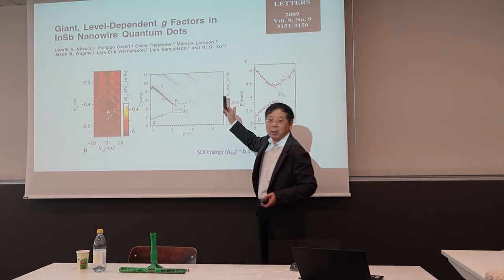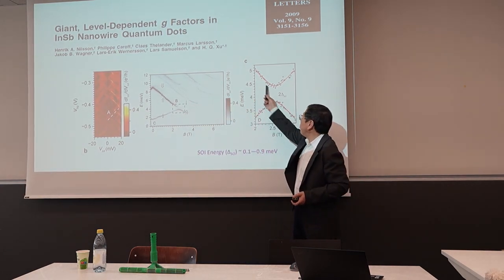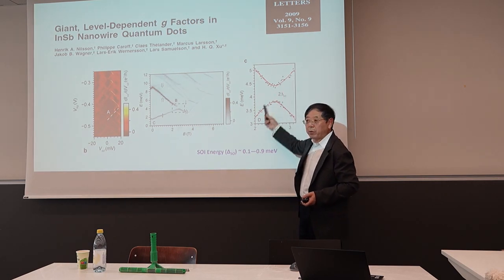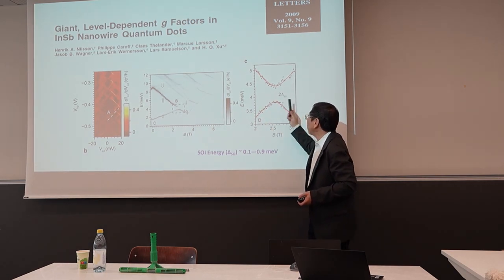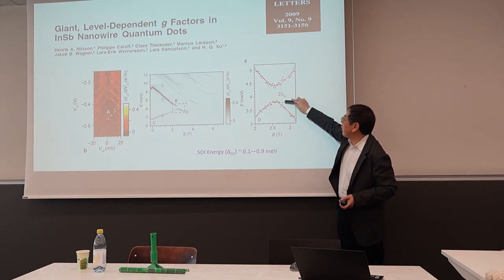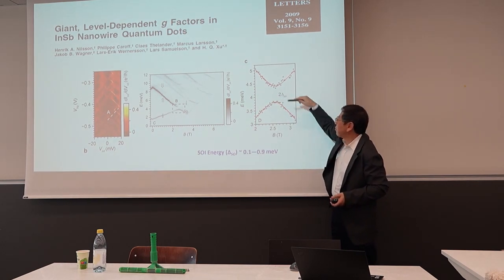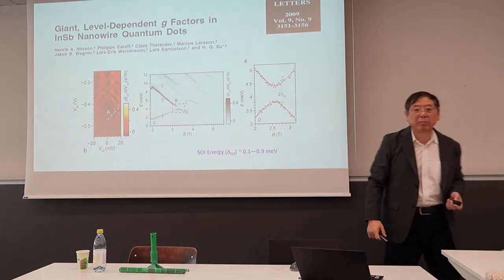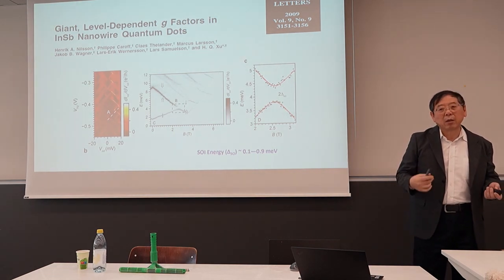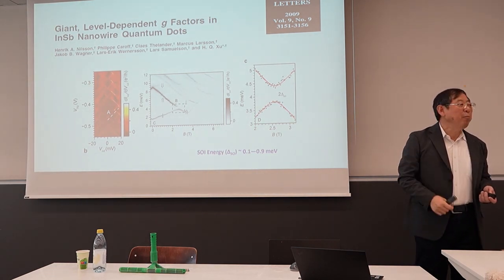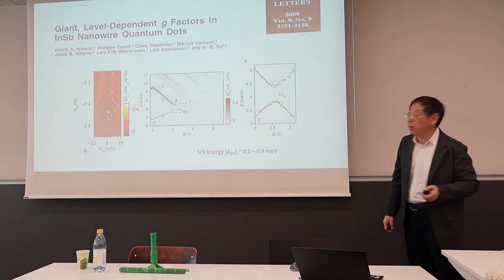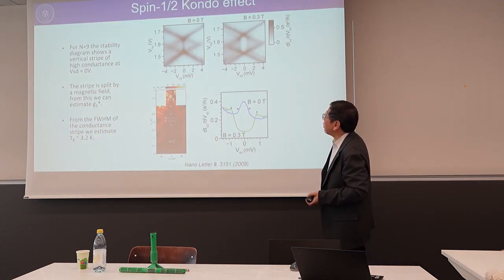Because of spin-orbit interaction. We can use a very simple two-level model to figure out how strong the spin-orbit interaction is. Then you fit the data and get the strength of the spin-orbit interaction, which we need to know in order to manipulate this state. But this is probably too much detail.